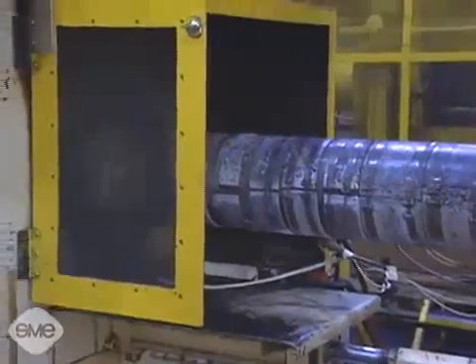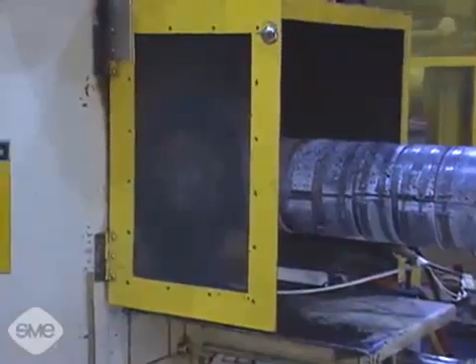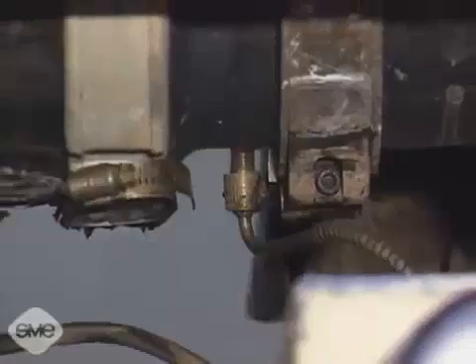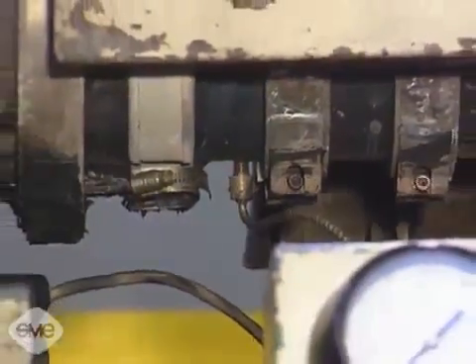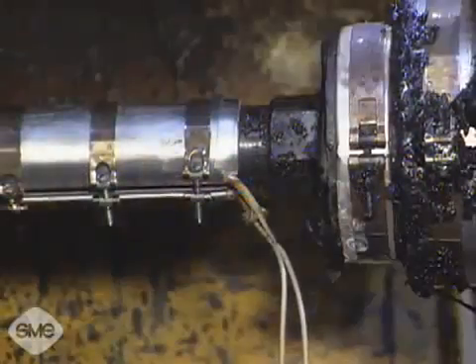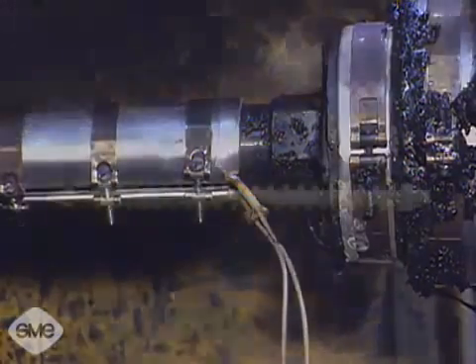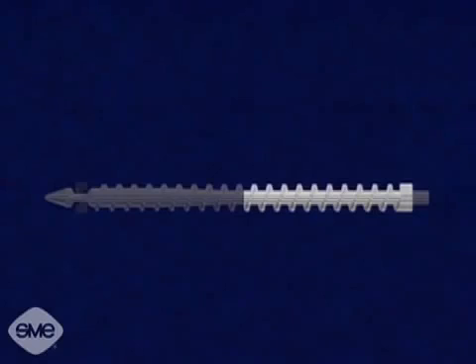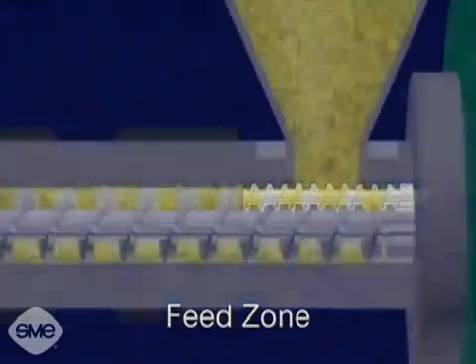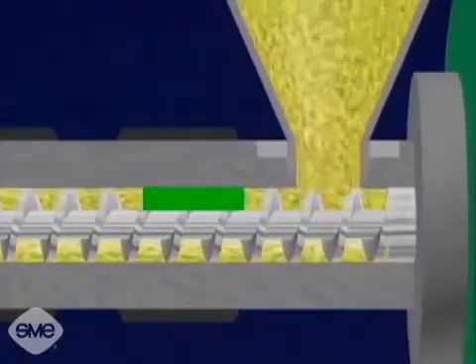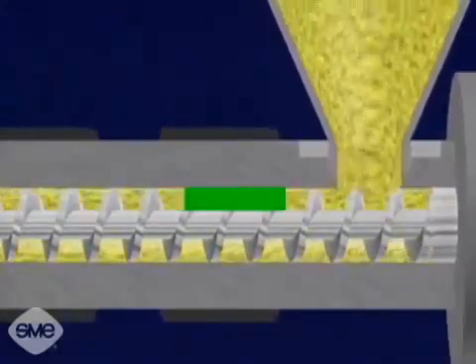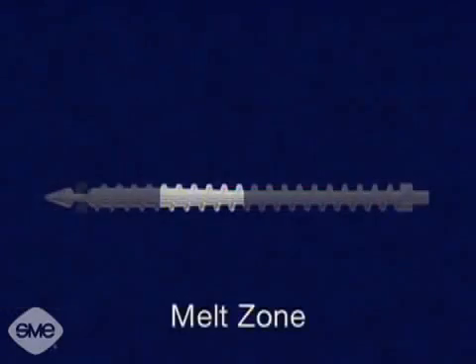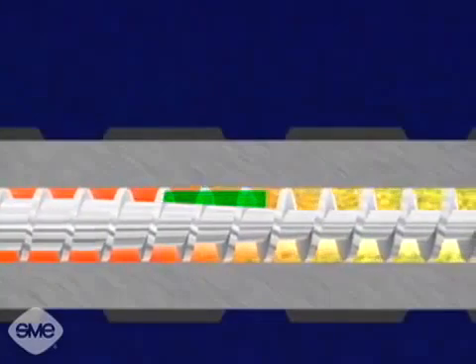The heating bands bring the material to its final temperature and compensate for the radiation heat loss. The temperature is controlled by three thermocouples in the barrel and one in the nozzle. The screw consists of three zones. The first zone, which is one half of the screw, is called the feed zone. It has a constant flight depth which forces the material together and rids it of air. The second zone, called the melt zone, has a decreasing flight depth which reduces the plastic volume. This causes the plastic molecules to rub harder against each other, plasticizing the material.